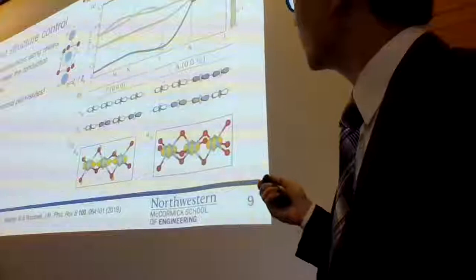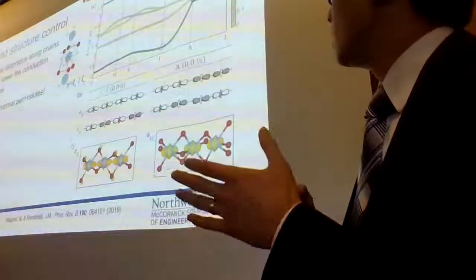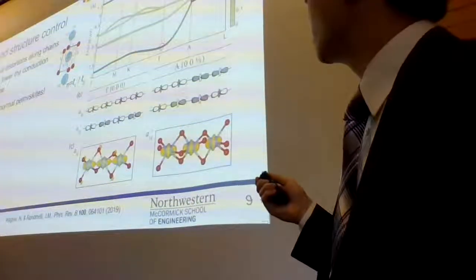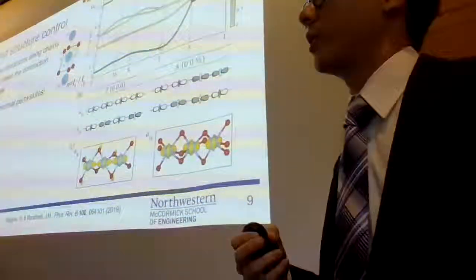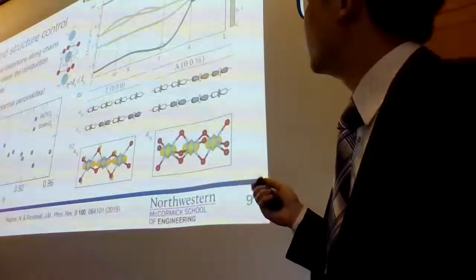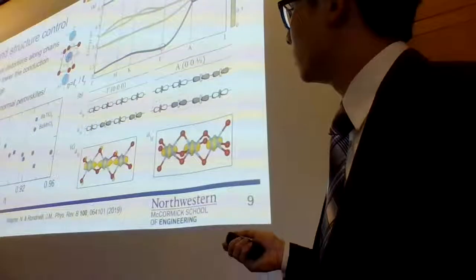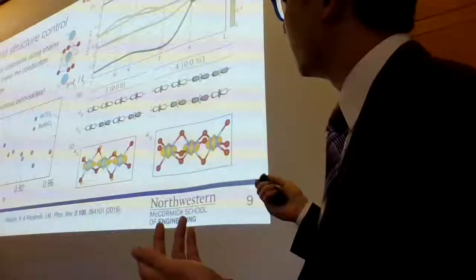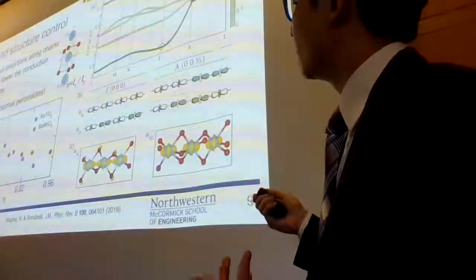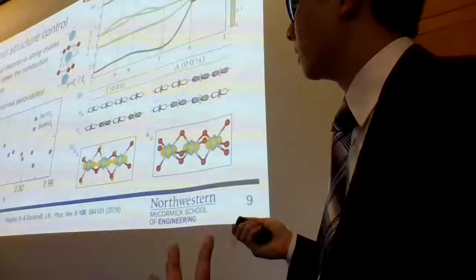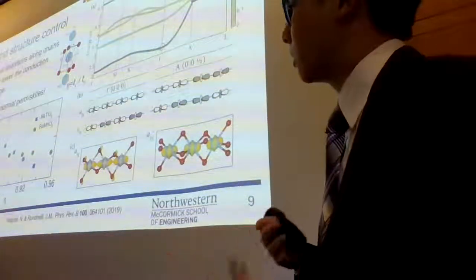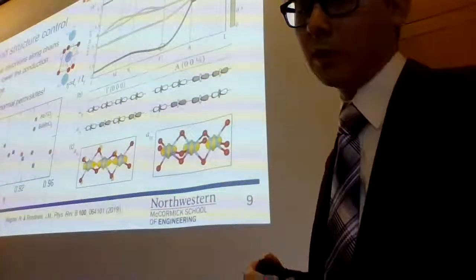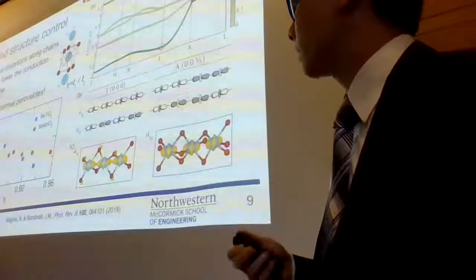And they lead correspondingly to a split in these bands in the conduction band. And the interesting thing is that as you compress the chains further together, as eta gets much larger than 1, this energy goes further and further down, this energy goes further and further up, but the end result is that your band gap is being shrunk as you do this. So you can see this effect is most pronounced in D0 titanates, because the bottom of the conduction band in this case, the A1G, is the lowest in energy. In the barium manganite, because they're D3, the band gap is not between A1G and the oxygen P states, but other metal states. So the effect there is much smaller.